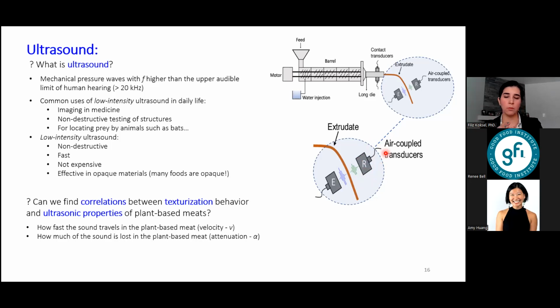And we're generally looking at two ultrasonic parameters to help us understand what's going on. So these two parameters are velocity and attenuation. Velocity is easier to relate to. It's how fast the sound travels in the plant-based meat. And attenuation is how much of that sound is lost in the plant-based meat. It could be due to scattering, it could be due to absorption. And the idea here is to, at the end, find some correlations between the texturization behavior of the plant-based meat alternative and the ultrasonic properties.